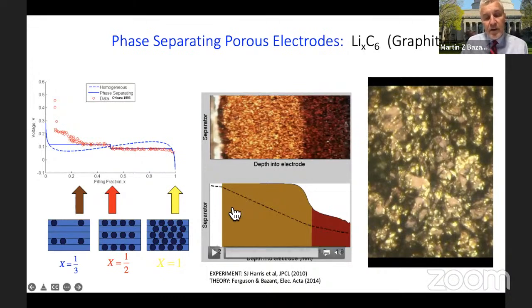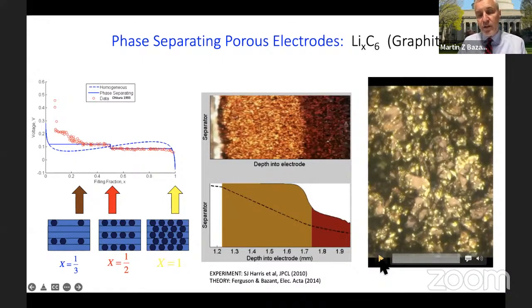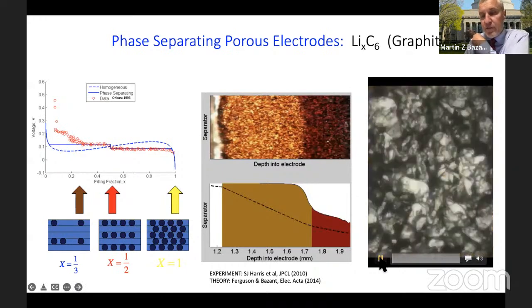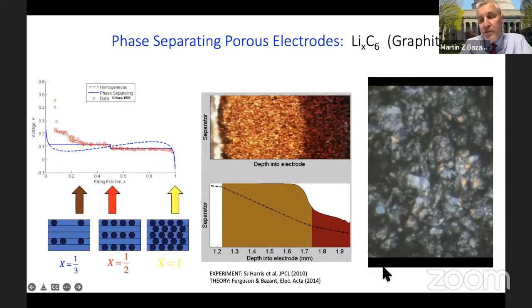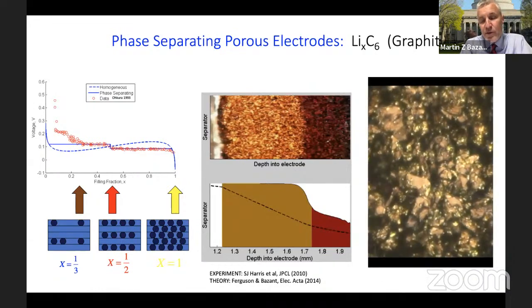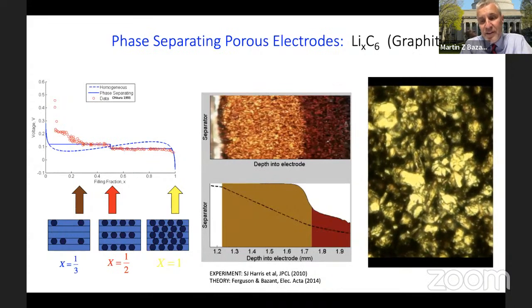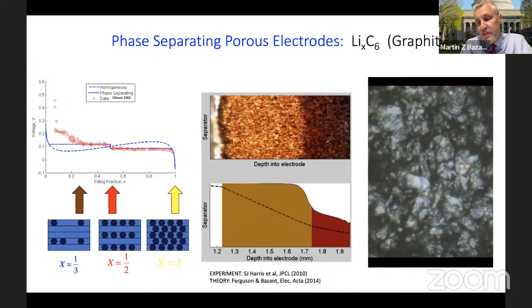And actually below that are synchronized simulations from a theoretical paper from my group in 2014 explaining this phenomenon at a macroscopic scale. But I think much more interesting is that in later work in collaboration with Samsung, they did experiments observing at a much smaller scale the dynamics of the phase separation. So they basically drilled a little hole in the back of the current collector in a real Samsung battery and observed lithiation in that system. And here's what you find. If you start with a system as empty, you first get the blue phase, which is 1/3, then you get the orange, which is 1/2, and then the yellow is 1 as the value of X in LiₓC6. So basically that's the concentration of lithium.